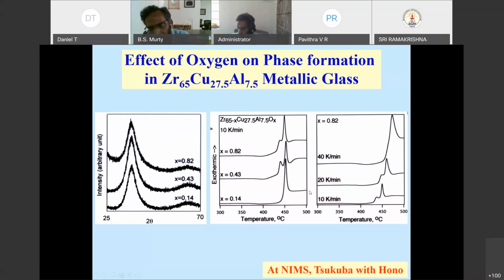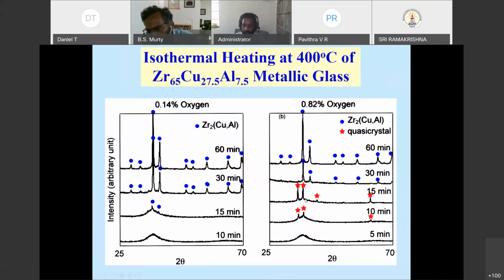And if you take this material and do some kind of a heat treatment inside the DSC or in a furnace and measure the XRD pattern, you will see that the alloy which has very low oxygen content, when you heat it from an amorphous state, it becomes a crystalline state. All these blue dots that you see, the peaks, are all basically Zr2CuAl.